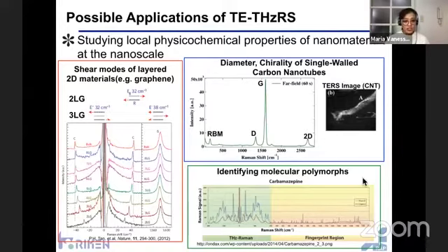Now, I think for me, the most interesting part for low frequency Raman is in the biological applications, particularly for medicine. Now, take for example carbamazepine, and if you look at the fingerprint region, or the 200 to 2000 wave number, if you compare form 2 and form 3, two kinds of carbamazepine, the fingerprint region or the Raman signature is totally identical. So it's very difficult to know, based on this fingerprint region Raman signal, if it's a form 2 or a form 3. But if you look at the low frequency, they are totally different. So here you can clearly determine which carbamazepine is in form 2 and which is in form 3.